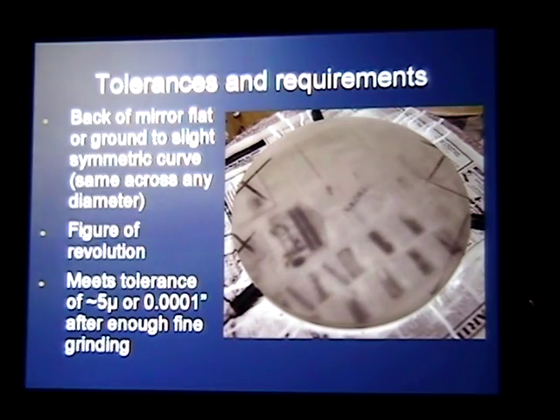So now that we have a piece of glass that hopefully doesn't have any strain in it or no significant strain, then we want to look at how do we prepare this piece of glass for high precision optical work. And this slide really tells you, and it kind of shows you graphically what you have to watch out for. So this is a blank that is just beginning to be ground on the back. So I have some newspaper underneath it here. Here are the 3 things that keep it on the mirror turntable. And you notice I had drawn a grid of marker lines, sort of like this, like a checkerboard pattern on here. And you can still see some of them right here. So what does that tell you?